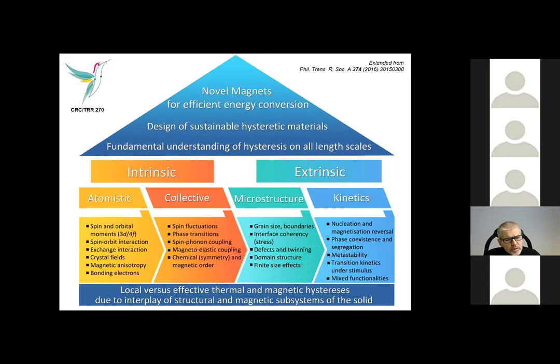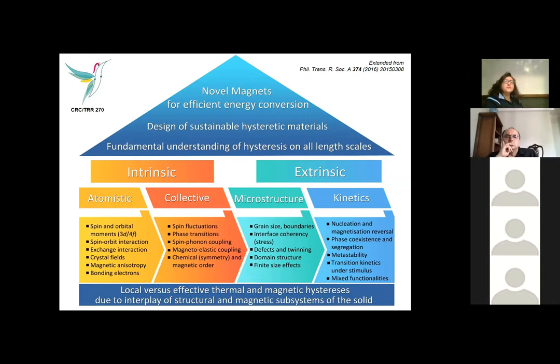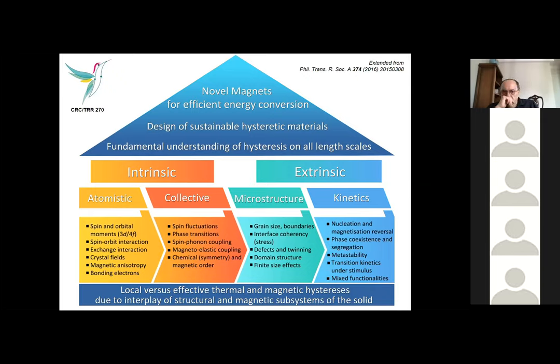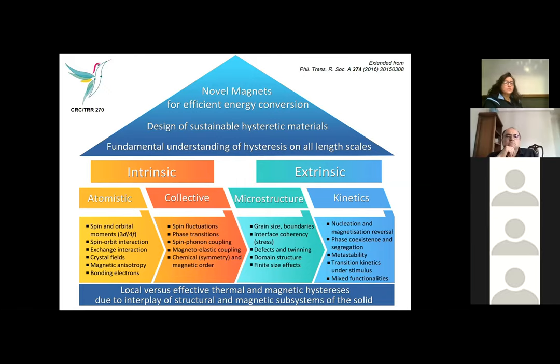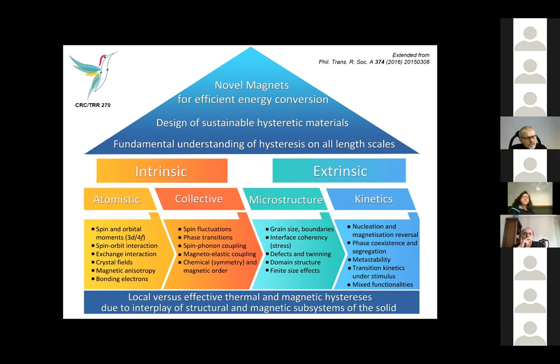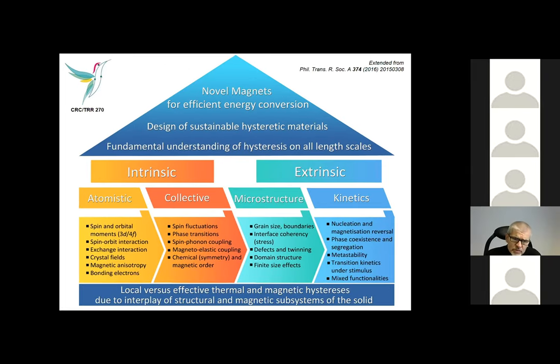We also designed here, or let's say summarized our ideas in the house of hysteresis. I won't go through all of it, but basically on the left-hand side, we look into the intrinsic parameters or contributors on atomistic and collective mechanisms. And then we also look into the extrinsic features like microstructure, defects, grain sizes, but also into the kinetics and the dynamics of magnetization reversal, or also the transitional kinetics of a magnetostructural transition in a Heusler alloy, for example, relevant for magnetocalorics. The idea is that we ultimately are able to manipulate locally and effectively thermal and magnetic hysteresis so that we can bring our novel materials to their physical limit.